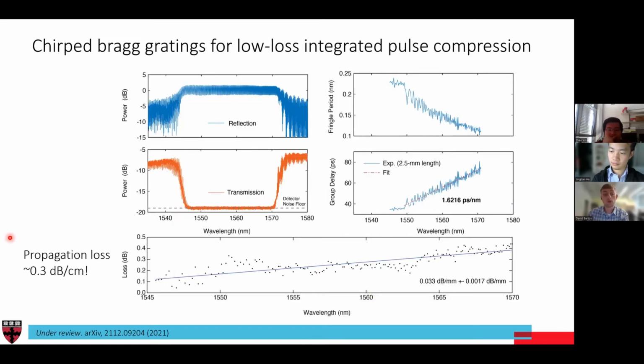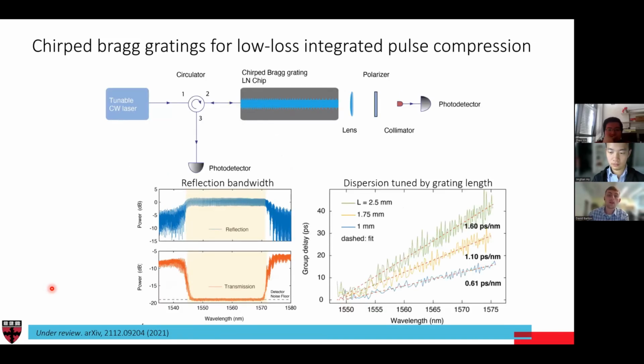The propagation loss is extraordinarily low. It's about 0.3 dB per centimeter, which is some of the lowest that's ever been reported in lithium niobate. We were able to change the dispersion here simply by changing the length. So for the given pulse that we want to compress, we can deterministically select how long we want this waveguide to be, and then go ahead and add it to our chip. And these are also very high reflectivity, so it's a very low loss structure.